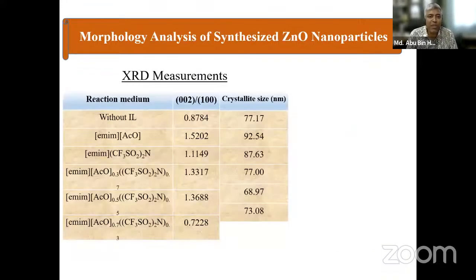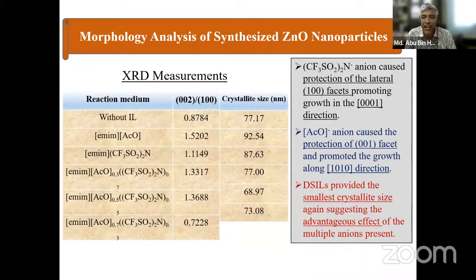And XRD measurement parameters are shown here along with the crystallite size. The bis(trifluoromethanesulfonyl)imide anion caused protection of the lateral 100 facets, promoting growth in the 0001 direction. This is interesting. And for the acetate anion, we see the protection of the 001 facet and promoted growth along the 1010 direction. That means two different anions actually controlled the growth process by two different mechanisms. So different phases, different growth directions.